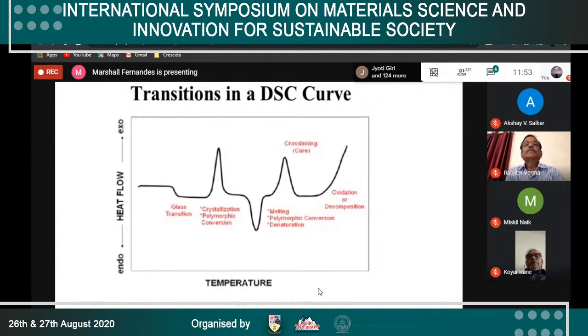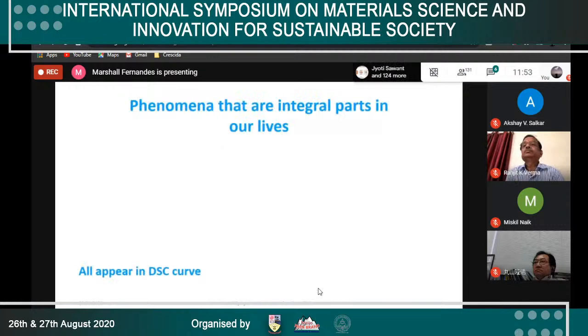So if you heat the fluffy mass, the citrate precursor, to a certain temperature, you find out up to what temperature we can heat, and see that the process of oxidation or curing is complete.